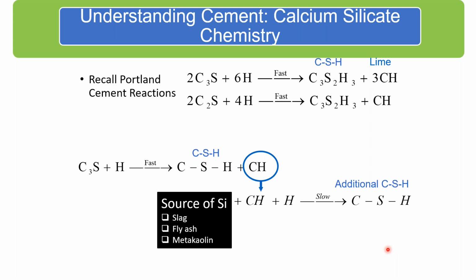Soon we discovered that I could use these as cement replacement instead of addition. And of course, then one has to get the math correct so that I can balance out the additional CSH against whatever it is that I'm losing with the reduction in C3S.